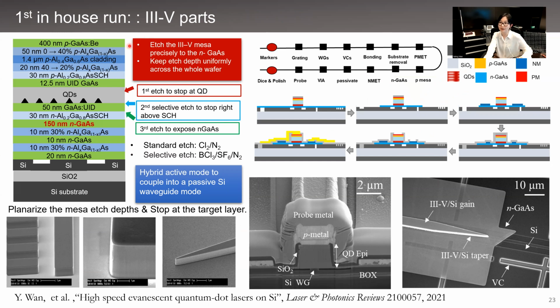So after the passive waveguide process and subsequent wafer bonding and the substrate removal process, there comes one of the primary fabrication challenges. So to etch the gain mesa precisely down to the 150 nanometer N-GaAs contact layer and keep the etching depth uniform across the whole wafer. So for indium phosphide-based devices, we have a highly selective wet etch that is available to planarize the mesa etching depth and stop right at the target layer. But this is unfortunately not applicable for AlGaAs and GaAs material systems with low aluminum content.